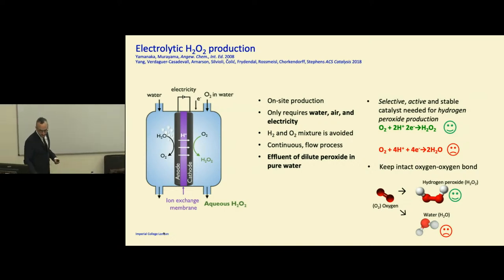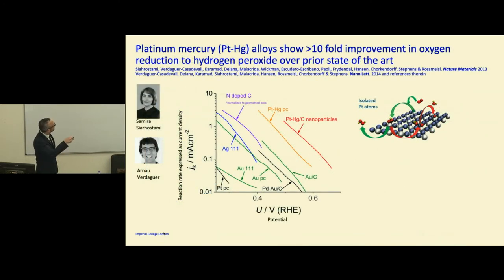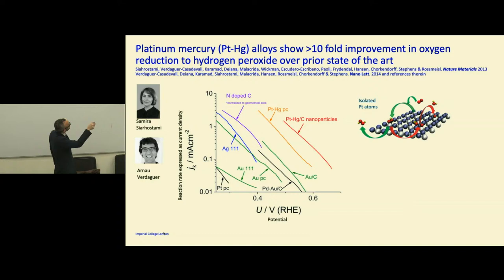So we had the idea of trying to do better. In particular, why not use a platinum-mercury alloy? What you can do is make an amalgam, so you electrodeposit mercury onto platinum, which makes a crystalline alloy at room temperature, and you have isolated platinum sites. What's really important to maintain this oxygen-oxygen bond is not to have two contiguous platinum atoms, because you need two contiguous platinum atoms to actually break the oxygen-oxygen bond. So if you have isolated atoms, you can end up making hydrogen peroxide.